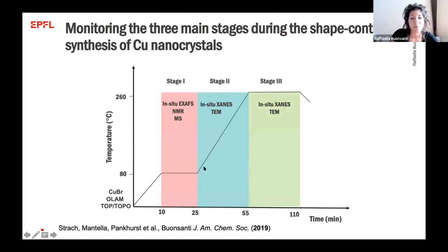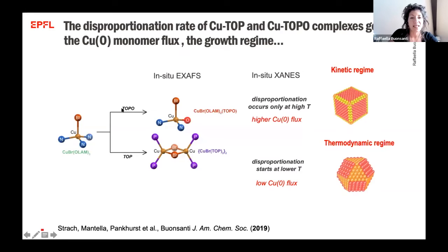And here, this is the temperature profile of the synthesis. So there is a heating ramp and a plateau, and we studied these three steps using in situ X-ray absorption, but also complemented with other ex situ techniques. And to make a long story short, what we learned is that the main role of the trioctylphosphine oxide and trioctylphosphine is to complex copper.